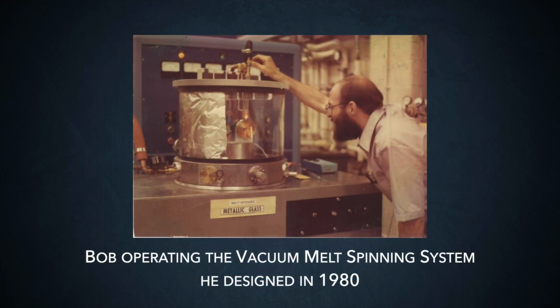And so that was the design I used. We came up using a big bell jar initially, with the top cut off, and then we put a big seal on the top and a steel plate. We used a big plexiglass plate on top that had the feed-through for our little quartz tube sticking into it, and the induction heater inside the chamber. And so that's the system that I designed.